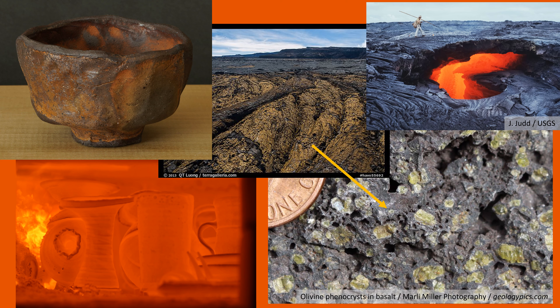Because the molten skin on the pots' surfaces is generally very thin, and cooling happens much faster than in a giant lava flow, the crystals are generally microscopic. But there can be a lot of them, and they can be strongly colored, so with our unaided eyes we tend to perceive patches of different kinds or densities of microcrystals as color and texture gradations over the surfaces of our pots.